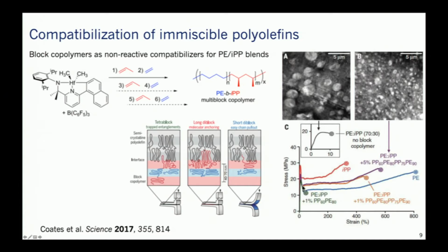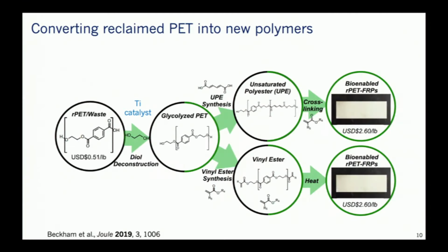But you can end up with materials that behave like the original polymers if you do this. Another approach, which is illustrated in this example from Greg Beckham's group at NREL, is a partial depolymerization followed by repolymerization. In this case, taking waste PET and doing a partial glycolysis. This is a titanium catalyzed process, and then repolymerizing with an unsaturated diester, which can then be cross-linked, and you can make new materials this way.